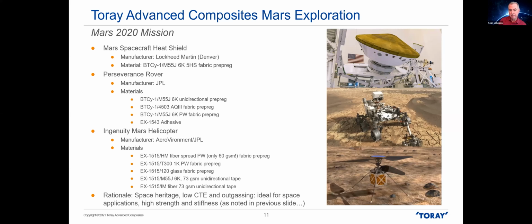BTCY1 is a 180C curing cyanate ester. And again, that reflects a lot of those properties we looked at. Low CTE, low CME, high resistance to micro cracks, very low outgassing, high resistance to radiation. And it has very good resistance to high heat, as you would see in the heat shield, or some of the electronics areas that it might be used in or protecting in areas like the heat shield or the Perseverance rover.